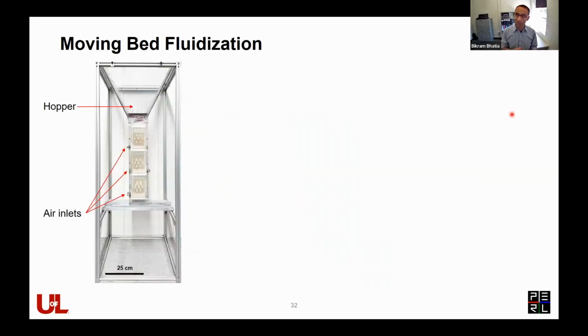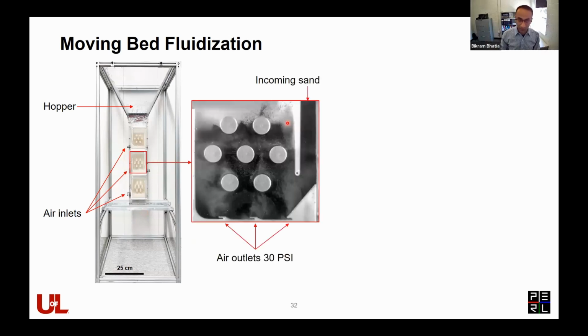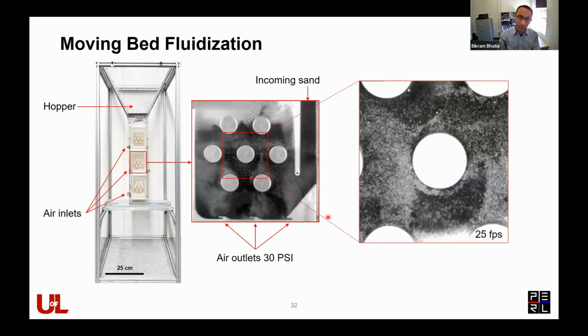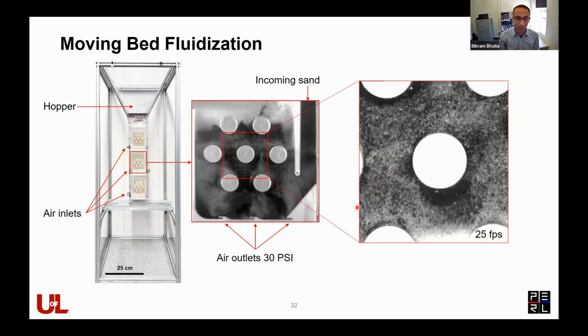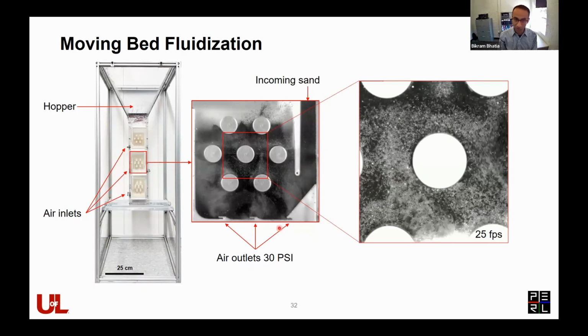So the first thing that we did was create this multi-stage moving bed fluidization heat exchanger system, where we built a setup with 3 stages, where the sand came in and was fluidized through air inlets at each of these stages. We looked at the particle flow around these tube walls as it went through different stages. We also have these air inlets on the bottom. Note that they have a cap on the top, which is quite typical in fluidized systems, to prevent the sand from blocking these air inlets, which almost causes the sand to flow in a clockwise direction. So they have this interesting directionality associated with it.